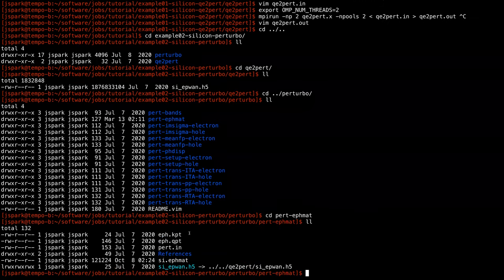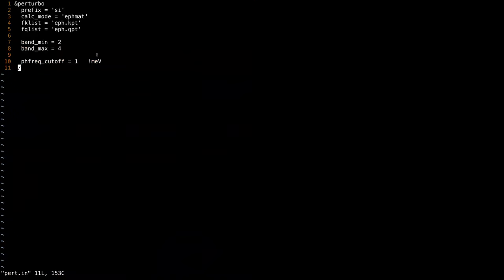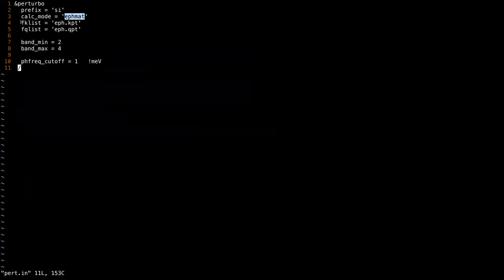Going into this folder, let's look at the input file, which is pert.in. The prefix should be set to the same as the one used in QE2Perturbo. In calc_mode we are using ephmat, which is the electron-phonon matrix elements interpolation. The fk_list and fq_list are the lists of k and q points to be interpolated. The band_min and band_max are the minimum and maximum bands to be summed over in the final electron-phonon matrix elements results. The ph_freq_cutoff is the cutoff frequency — if the phonon frequency is less than this energy, the electron-phonon matrix elements will automatically be set to zero.